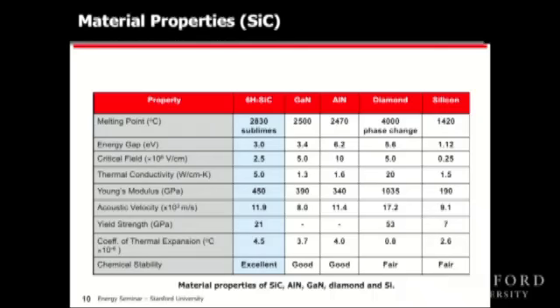So you may be thinking, well, why not diamond? It has excellent mechanical and electrical properties. Diamond, when you expose it to hot oxidizing environment, it actually turns to graphite. So it's not suitable for environments such as a combustion environment, for example. And later on in this talk, I'll talk a little bit about gallium nitride and aluminum nitride, which are emerging materials, which are also wide bandgap, but they're also piezoelectric materials, which are interesting for sensor design.